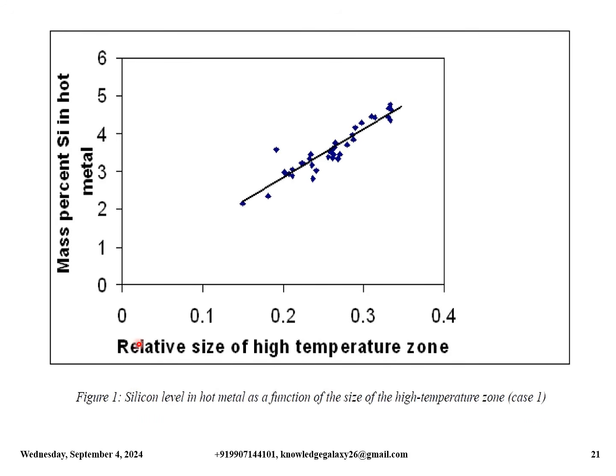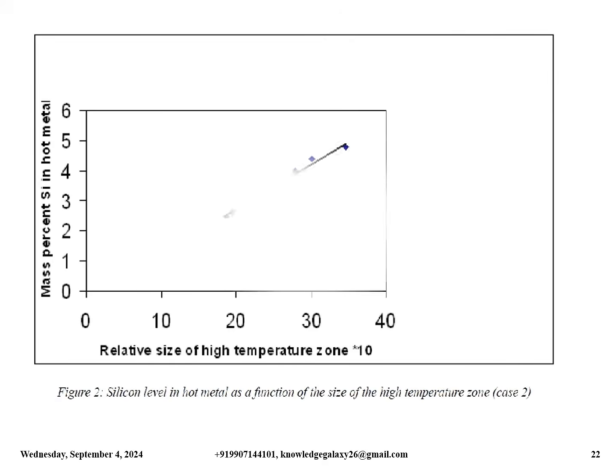So this is figure 1, which shows the silicon level in hot metal as a function of the size of the high temperature zone in case 1. You can observe that this is a linear relation, which I have just explained. And this is figure 2 for case 2. The same linear relation is observed.